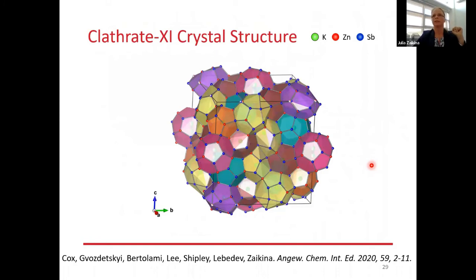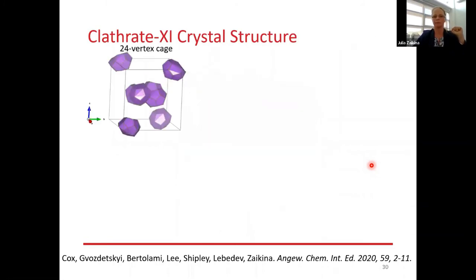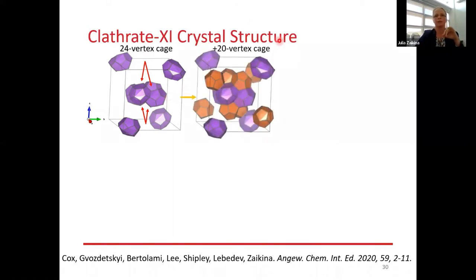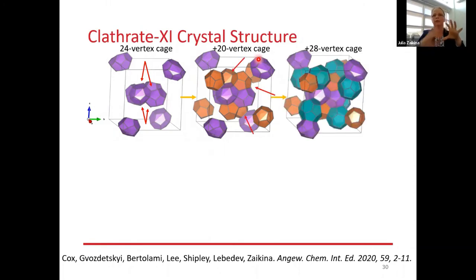Now, this is a very beautiful crystal structure of that clathrate. There are 3 types of cages in the structure. It's a 24 vertex cage made out of covalently bonded zinc and antimony atoms, and those cages are filled with a single potassium cation. And then those cages come together with the 20 vertex cage. And then we add the even larger 28 vertex cage, and the potassium cation is really quite unhappy in this because the cage is too large, so it is rattling inside the cage.